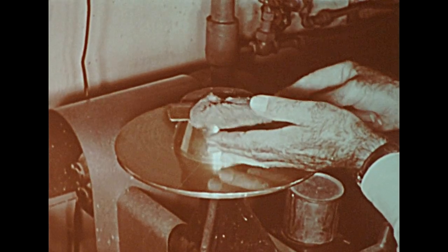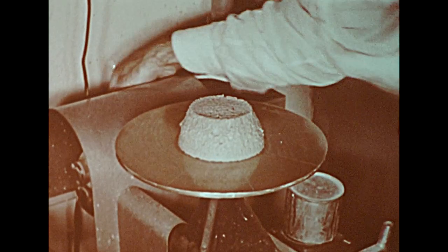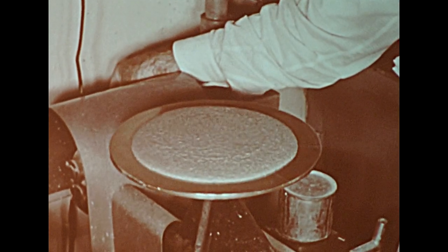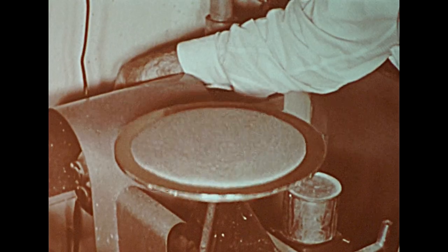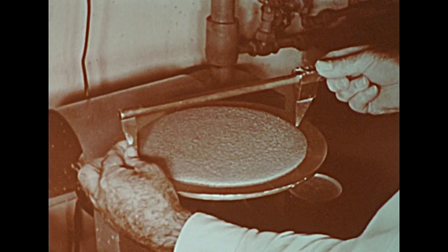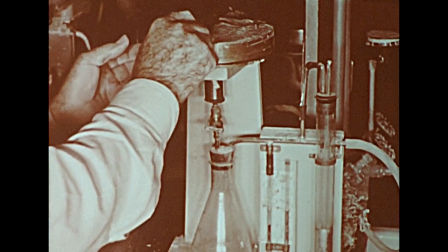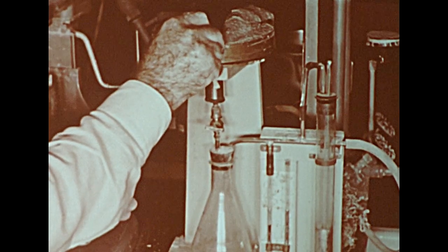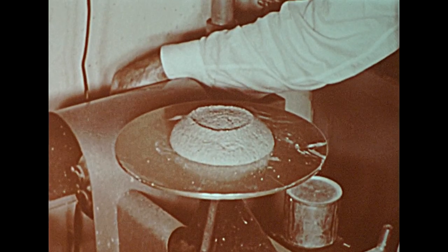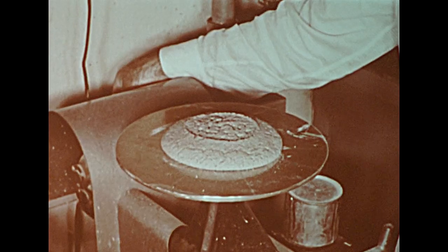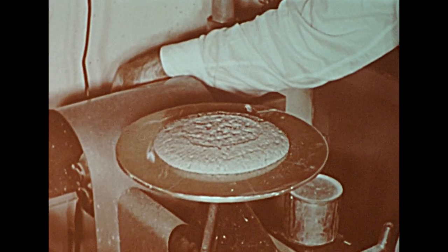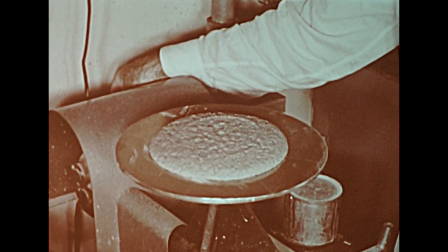Now for the lime Portland cement mortar. 2 parts lime, 1 part Portland cement, and 9 parts sand. The initial flow measures 103. The flow after suction measures 91, for a water retention value of 88%.